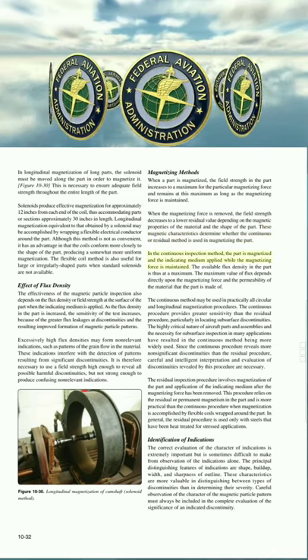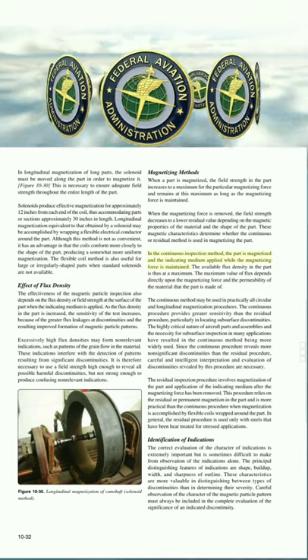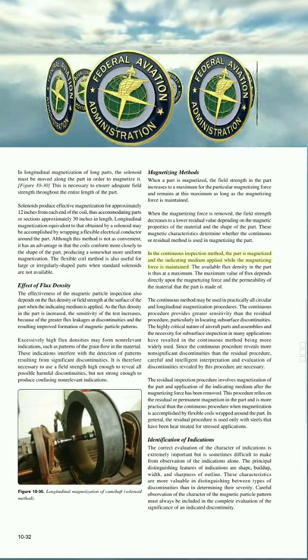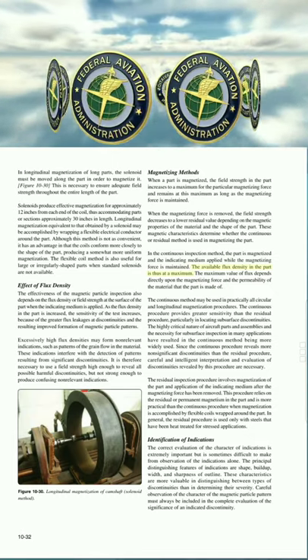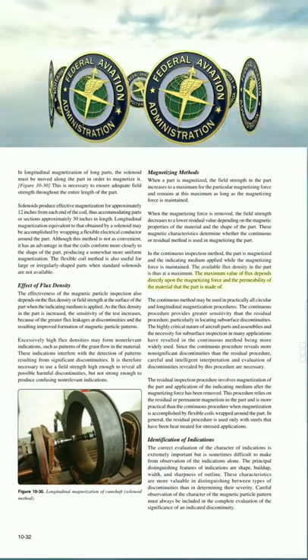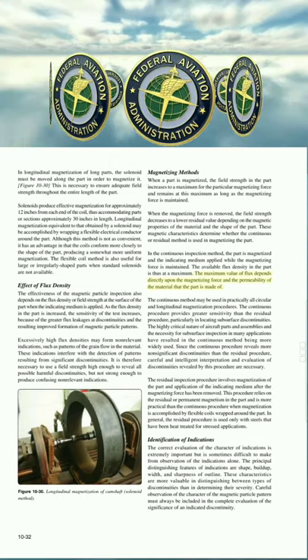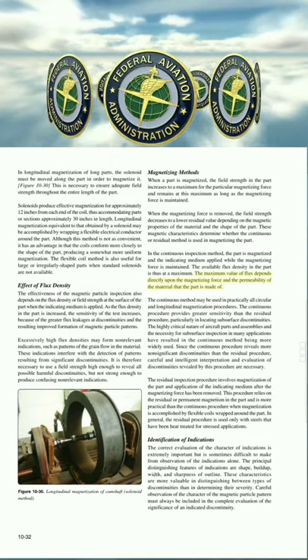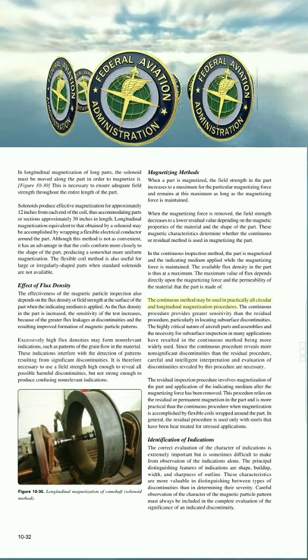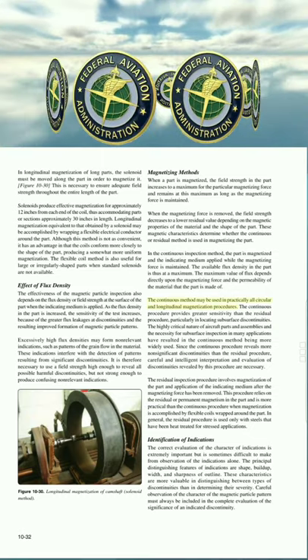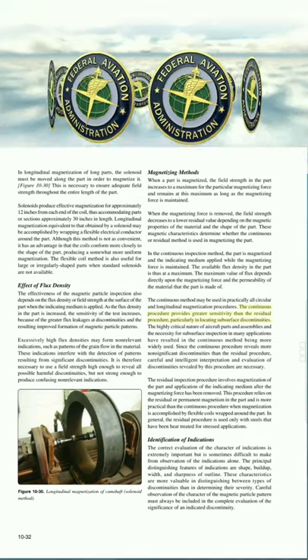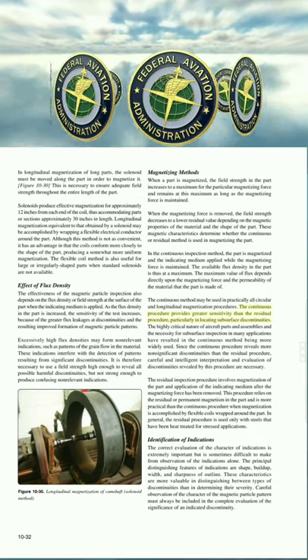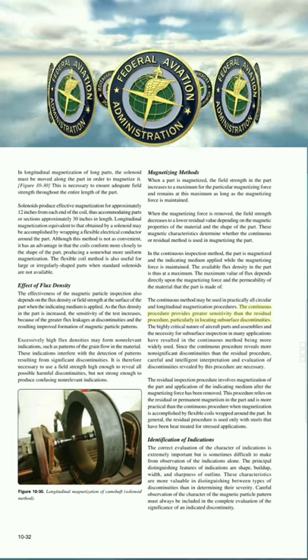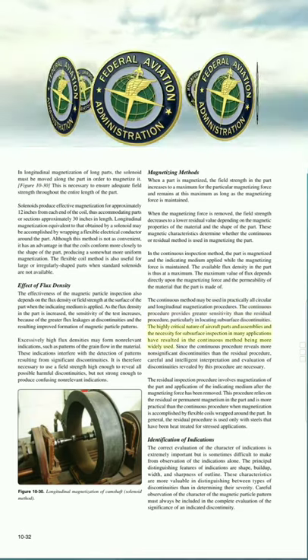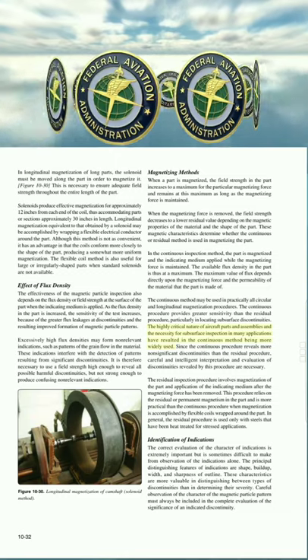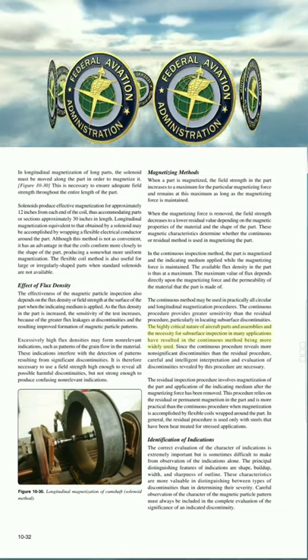In the continuous inspection method, the part is magnetized and the indicating medium applied while the magnetizing force is maintained. The available flux density in the part is thus at a maximum. The maximum value of flux depends directly upon the magnetizing force and the permeability of the material that the part is made of. The continuous method may be used in practically all circular and longitudinal magnetization procedures. The continuous procedure provides greater sensitivity than the residual procedure, particularly in locating subsurface discontinuities. The highly critical nature of aircraft parts and assemblies and the necessity for subsurface inspection in many applications have resulted in the continuous method being more widely used.